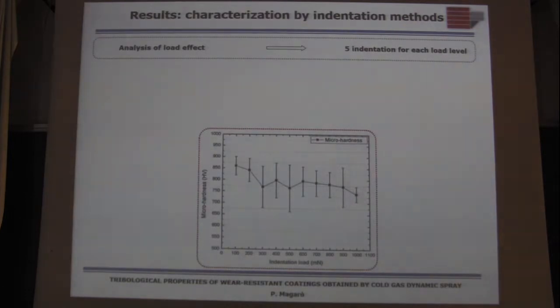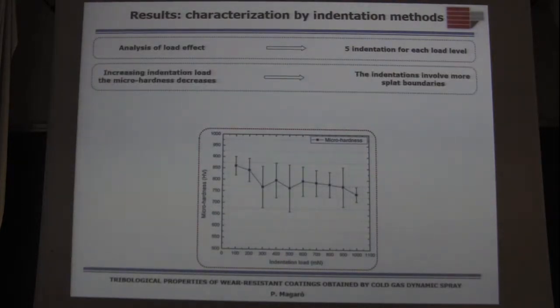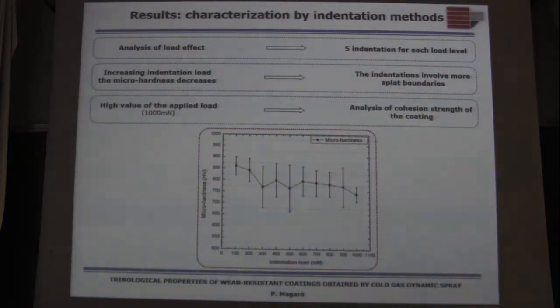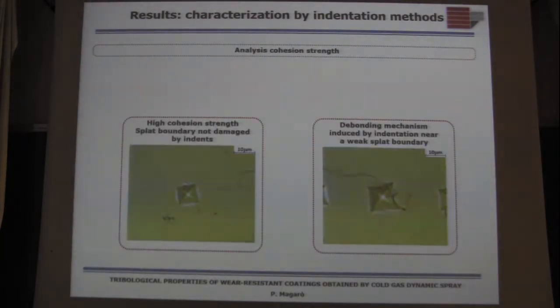Another kind of characterization was carried out on the cross-section of the coating in order to analyze the properties of the deposited layers. At first, the load effect was analyzed, and 5 indentations were carried out for each load level. We can observe that with increasing indentation load the micro hardness decreases, so we can see that the indentations involve more splat boundaries. For this reason, we have set the applied load used for the characterization equal to 1000 millinewtons.